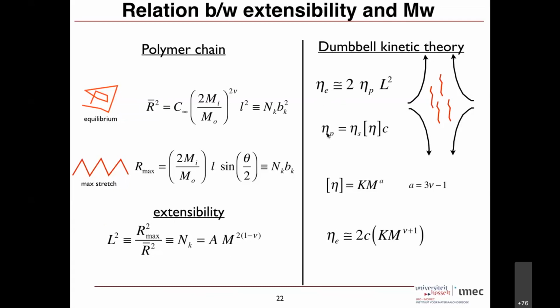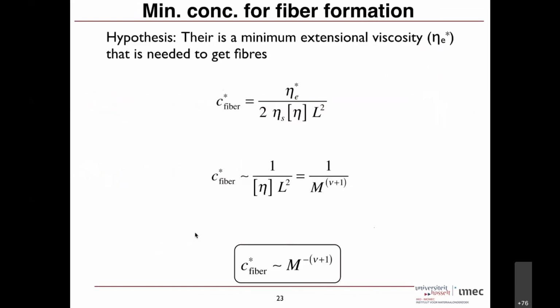And the polymer viscosity depends on the viscosity of your solvent. If it's ethanol, the viscosity of ethanol. Something called intrinsic viscosity, which depends on the molecular weight. And the concentration, how much polymer you put in. And you put all this together, then you're going to get extensional viscosity as some kind of a function of molecular weight, what kind of solvent it is, does the molecule like the solvent or not, that number tells you that, and the concentration. So you combine these two, and you make a hypothesis.